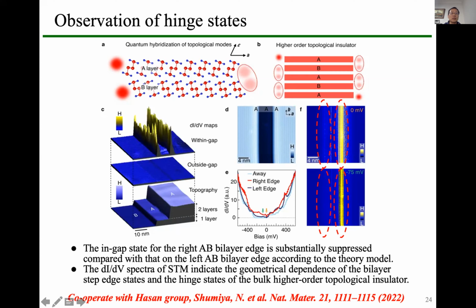If we look at the structure of the bilayer, we will find that the edge state should cover here and here. But because the edge has a different structure at the two ends, we come back to the higher order TI. Then we will find that in this structure, we have a very strong hinge state here, and here we don't have any significant edge state. So this picture was confirmed in experiments.